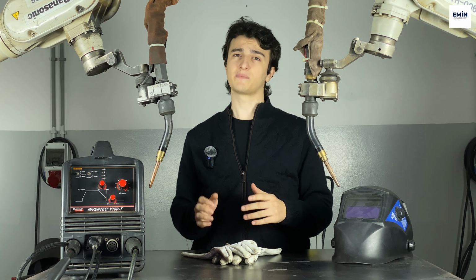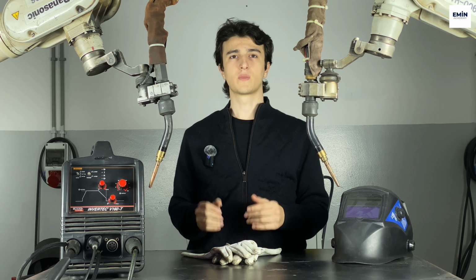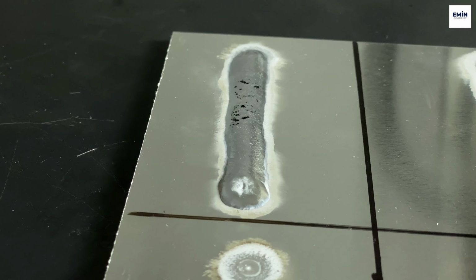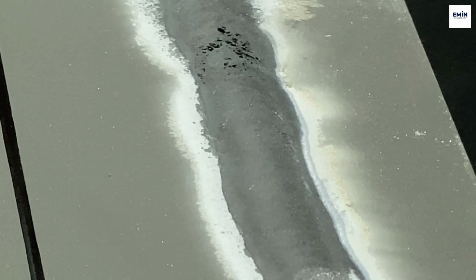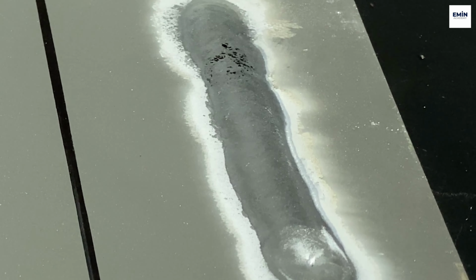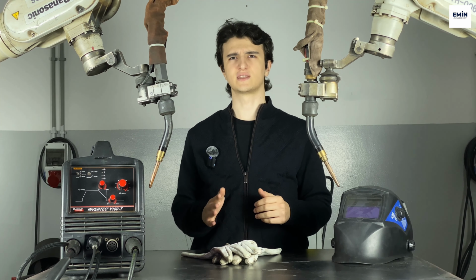So, what happens if the balance settings are adjusted incorrectly? The oxide layer won't be broken down sufficiently. The weld bead will look dull and dirty. Penetration weakens, tungsten life is shortened, and the risk of porosity and defective welds increases.